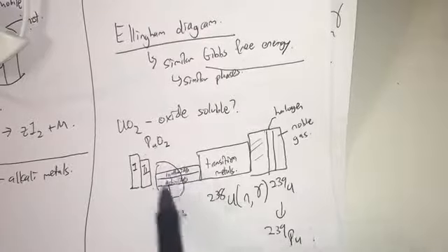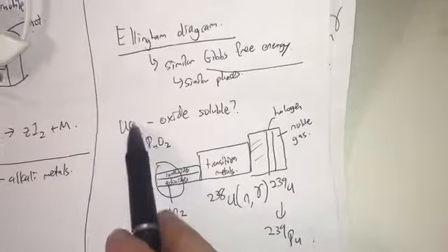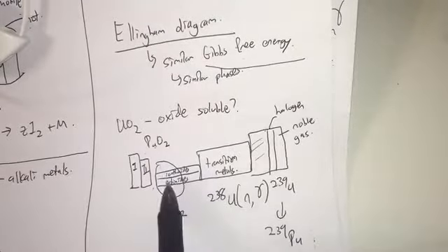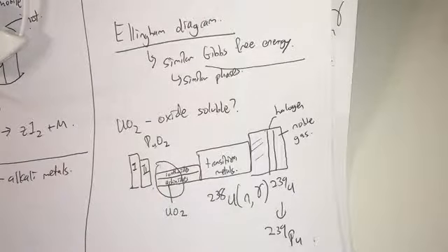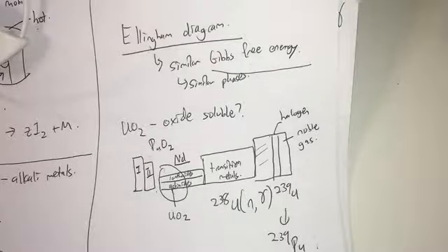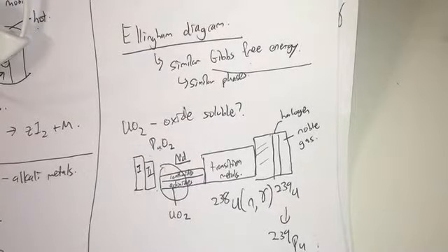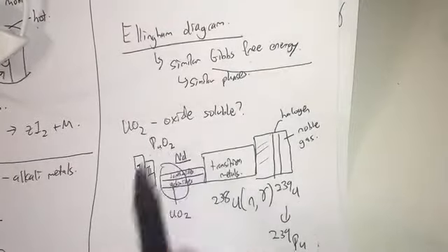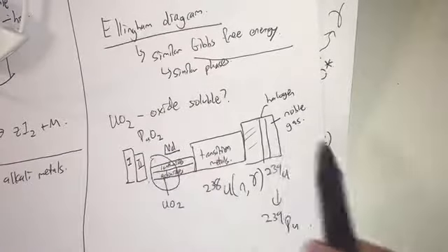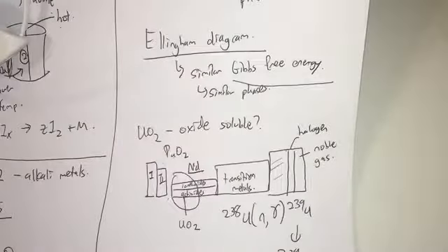So in this lanthanide, actinide phase, you have uranium, you have plutonium, you have rare earths as well, things like neodymium. All will be found here inside this uranium oxide phase. And sometimes a limited amount of molybdenum and zirconium will dissolve here as well. They have limited solubility.